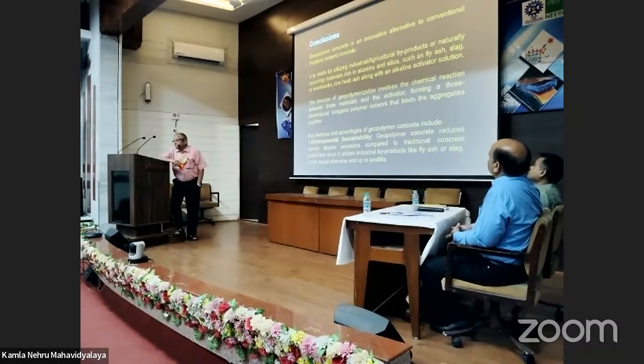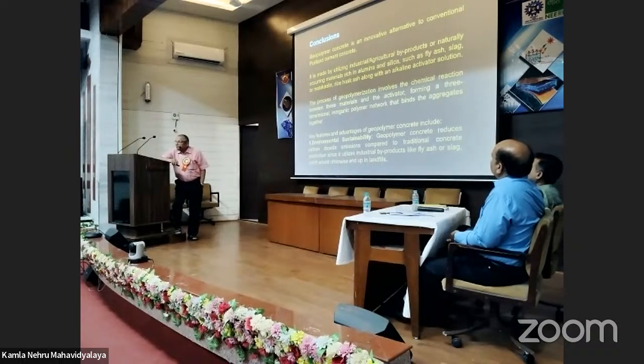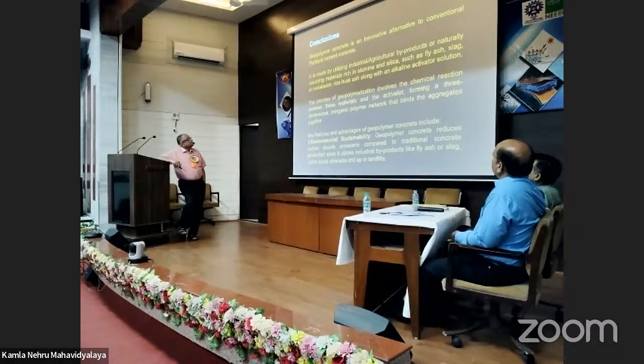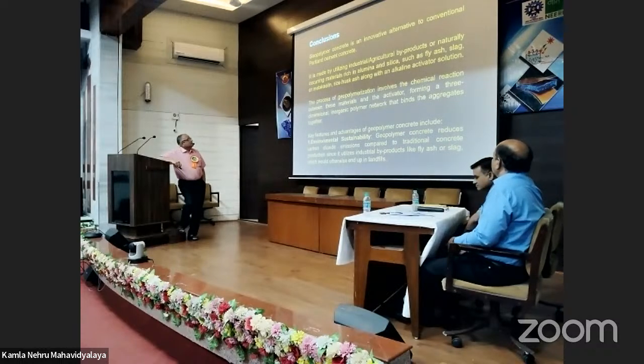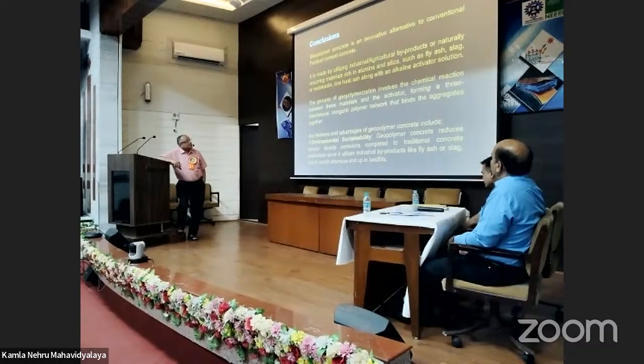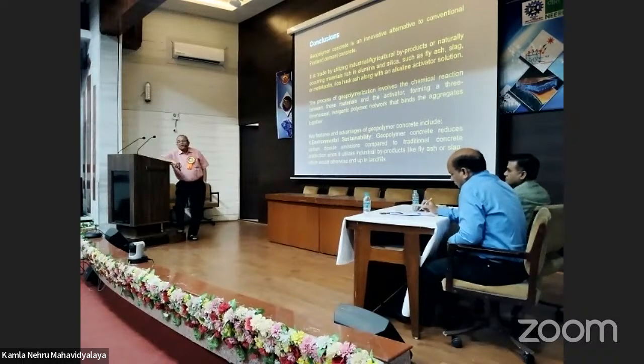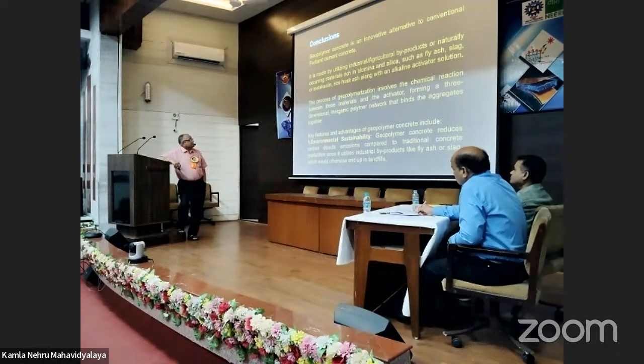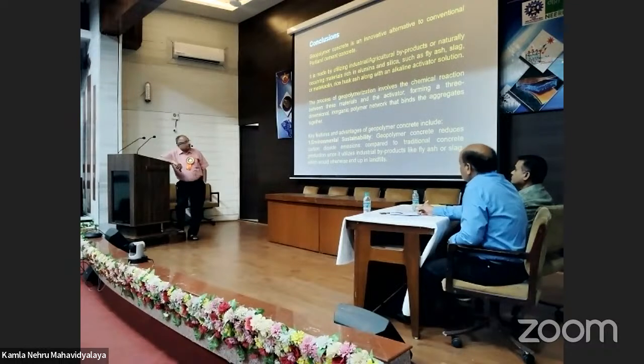Now, considering all this information which I have just presented, we can have some conclusion. Geopolymer concrete is an innovative alternative to conventional Portland cement concrete. It is made by utilizing industrial, agricultural byproducts or waste material or naturally occurring material rich in alumina and silica, such as fly ash, slag, or metakaolin, rice husk, along with an alkaline activator solution. The process of geopolymerization involves the chemical reaction between these materials and the activator, forming a three-dimensional inorganic polymer network that binds the aggregates together.